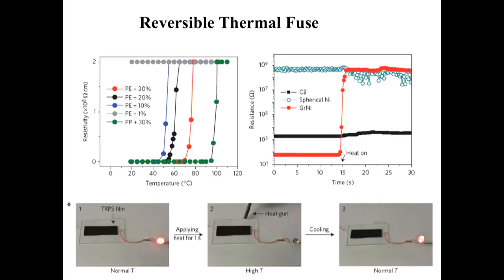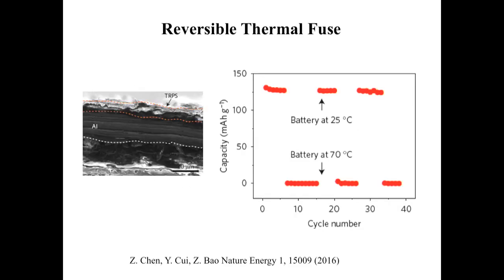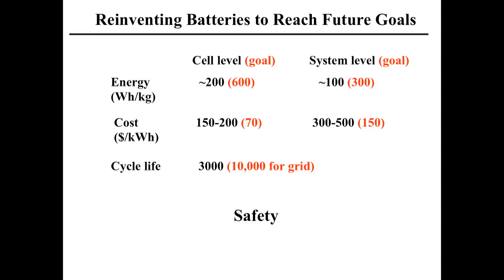So we test this out. If you blow the heat gun right here, this becomes not conducting anymore. This LED goes off. So we build our batteries: at regular temperature, you can get capacity out. Once you heat it up, there's no capacity coming out. So you have a thermal fuse right there. It's reversible. If the temperature comes back to room temperature, it works again. So an idea like this might help us solve the battery safety problem in a very different way.